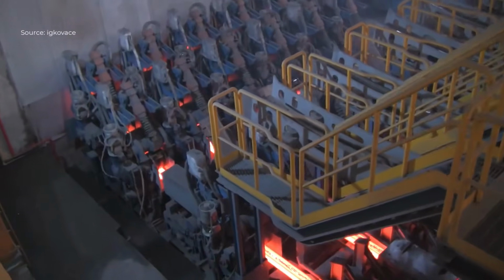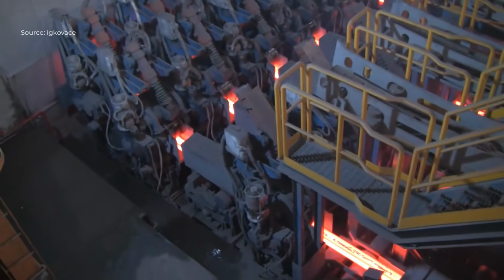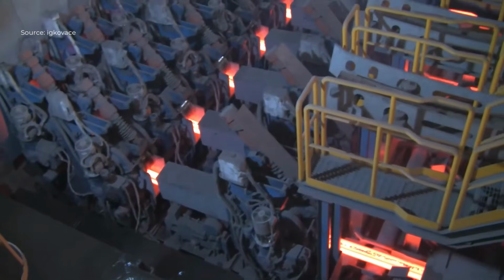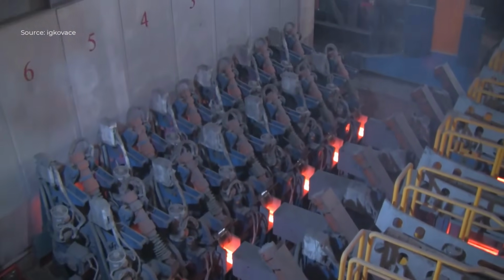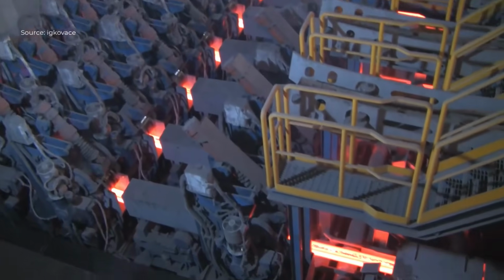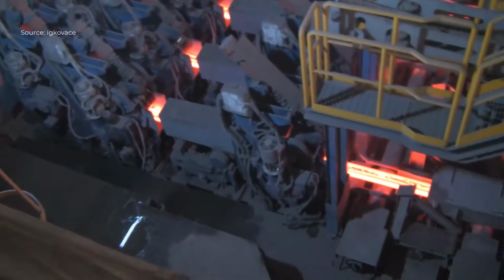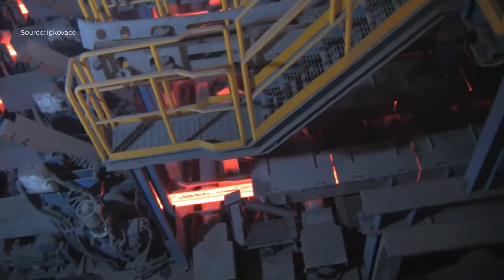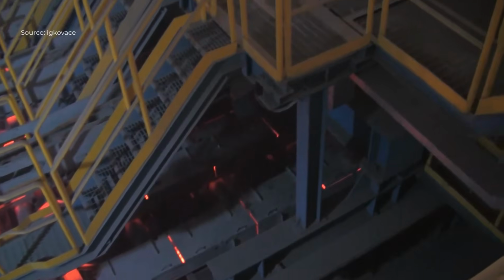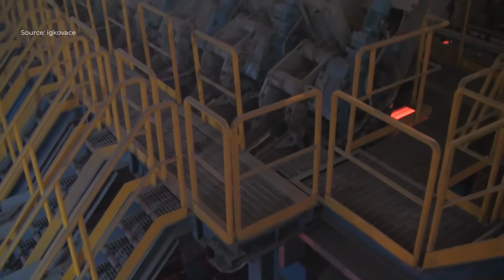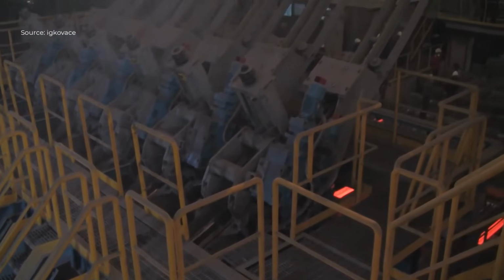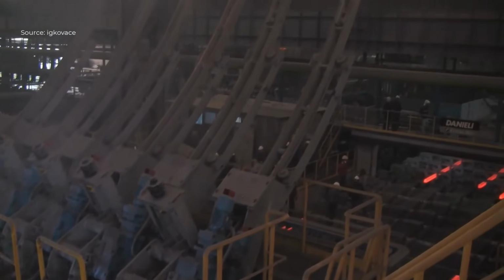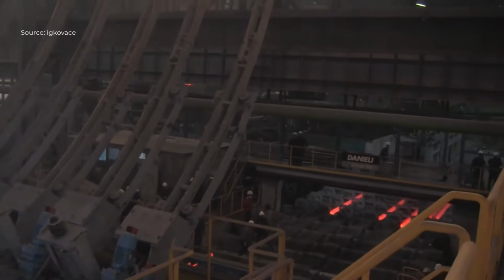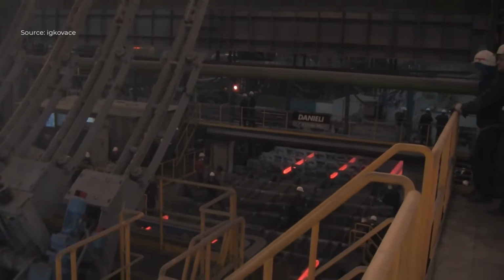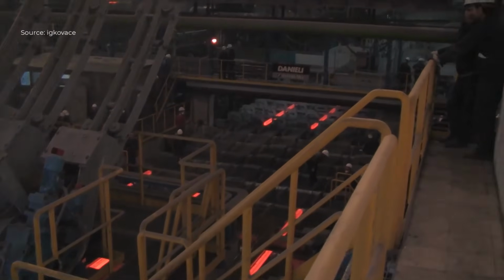The hot test steel rolling mill marks a crucial stage before full-scale production begins. During this phase, the entire system, from reheating furnaces to rolling stands and cooling beds, is tested under actual operating temperatures. Red-hot steel billets are heated to over 1,000 degrees Celsius and pass through a series of rolling stands to ensure proper shaping, alignment, and thickness control.